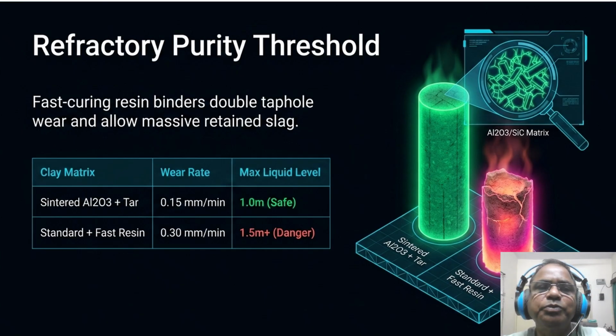Fast curing resins are popular because they save time, but look at the cost. They double your taphole wear rate. This allows for massive retained slag in the hearth because the hole enlarges too quickly during the cast. And here a campaign life issue is also occurring. So by choosing the high purity sintered alumina matrix, you maintain a safe liquid level of 1.0 meter. If you use the fast resin shortcut, you are consistently operating in a 1.5 meter danger zone, inviting premature erosion of